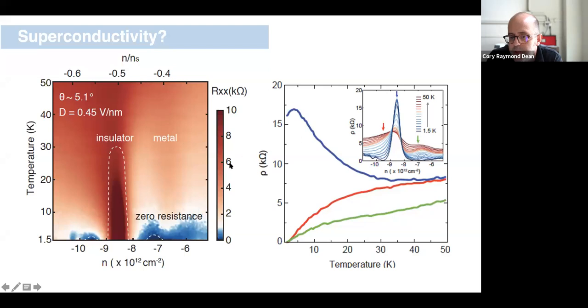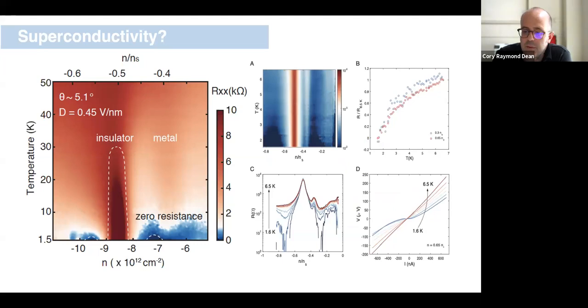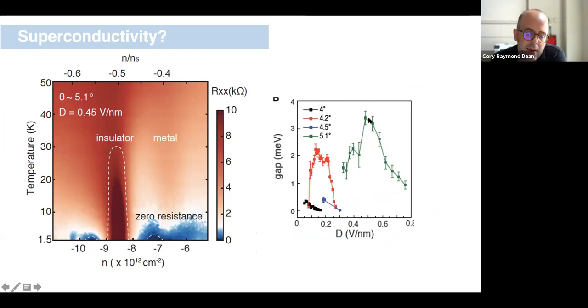It's not very clear. One of the challenges of this particular system, as I keep emphasizing, is that contact resistances are rather terrible. So we're trying to make an assessment about whether we have superconductivity in a system where generally we might find that our two-terminal resistance could be as high as 100 kilo ohms in some devices. So it's a little bit fraught to make very specific claims. What we did notice is that this particular device, which is the only device in which we measured something that might possibly indicate superconductivity, is the same device in which we measure the strongest insulating gap. So that might be suggestive that, if there is superconductivity at all, it might be manifesting in systems where we have the strongest electron correlations in the band, if we take the size of the insulating gap as somehow indicating the strength of correlations in the band.